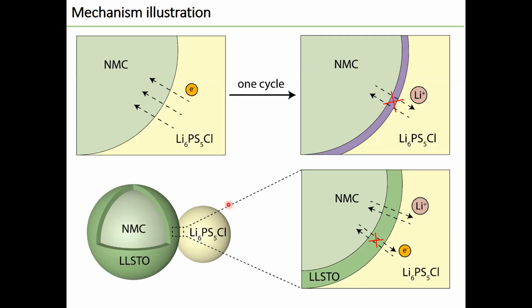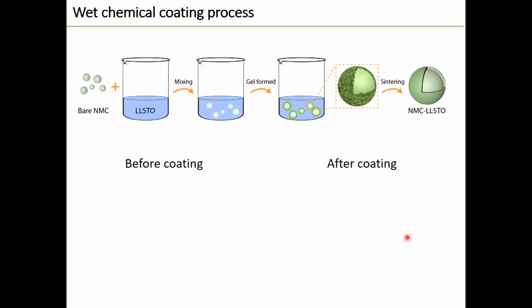However, when we coated a thin layer of LLSTO on NMC, NMC was insulated from the sulfide electrolyte, which avoids the chemical reaction. More importantly, the LLSTO layer enables high ionic conductivity and electron insulation, which avoids the electrochemical decomposition of the electrolyte and much decreases the interface resistance.